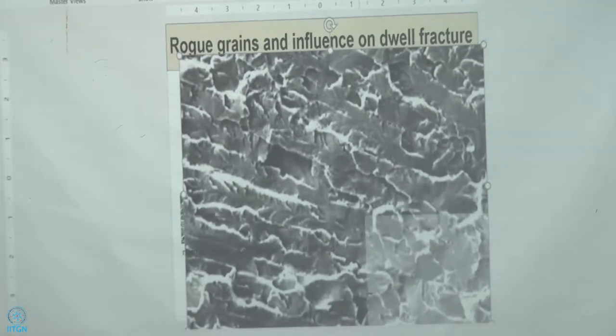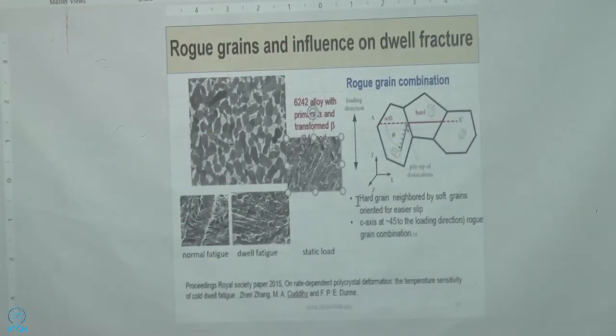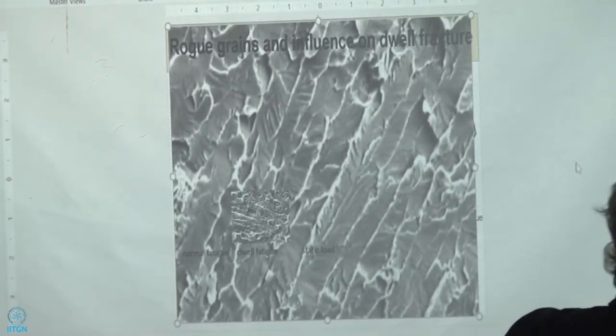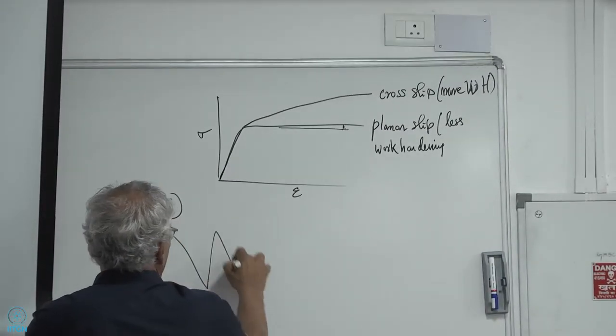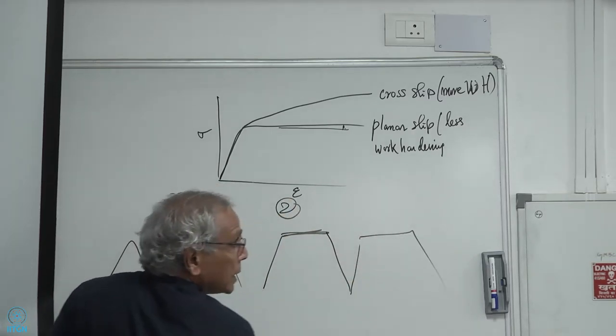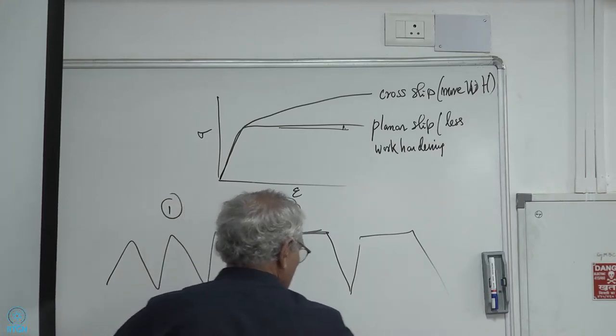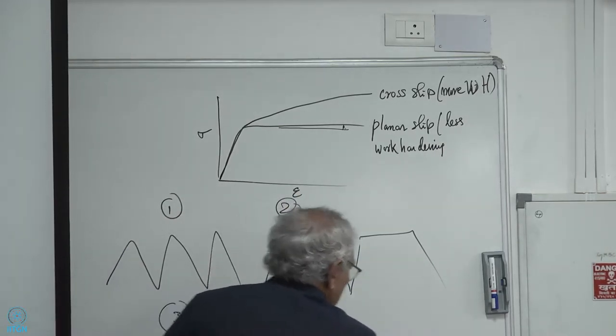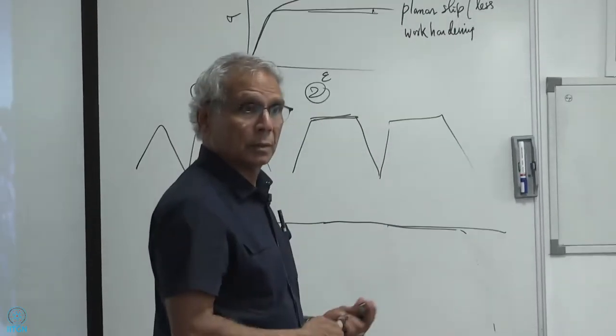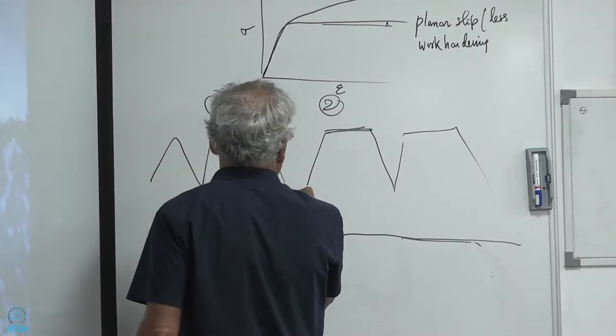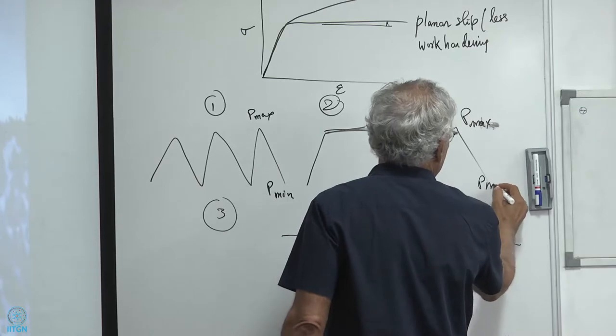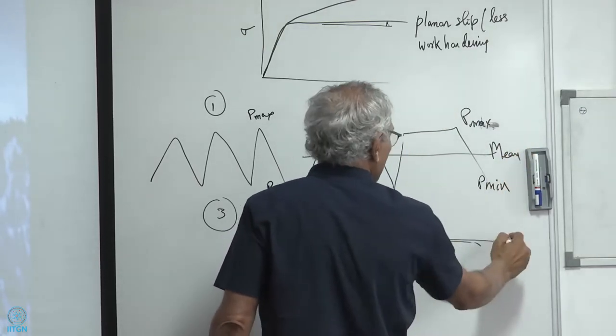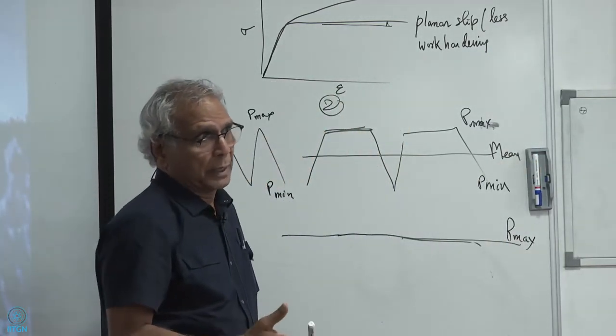Okay, so that's good. Now, I said the other day, creep occurs at room temperature in titanium. It does occur at room temperature, but you only see the primary creep, not the secondary and the tertiary. Only a small portion of the primary takes place at room temperature. Significant strain can accumulate during creep as a function of time at room temperature. So Neeraj, Mike Dane, Glenn Dane, and Mike Mills, these are the three guys from Ohio State University. I believe it's this guy's PhD thesis, because Glenn and Mike are professors, I know them pretty well.